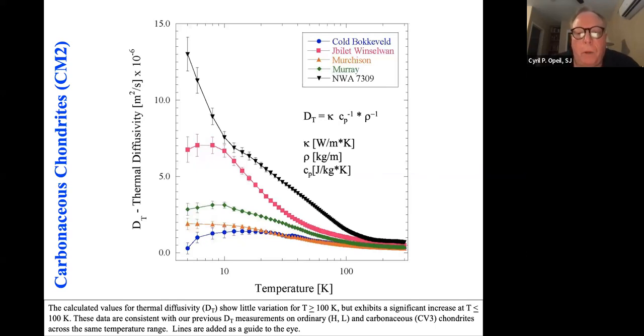I believe this may certainly be the first carbonaceous chondrite thermal diffusivity going from 300 Kelvin down to basically 5 Kelvin. We notice that at high temperatures above 100 Kelvin, very little changes. However, as we go below 100 Kelvin, we see that the thermal diffusivity rises significantly for the different materials. I haven't found anything this cold in any literature, but in terms of these temperatures, these are typical curves, and it is important to see that these materials are behaving in this fashion.